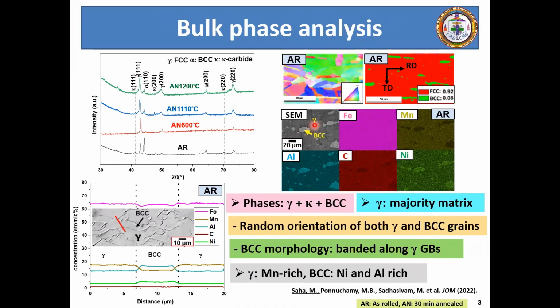and we can clearly observe that the gamma phase, the majority matrix, is enriched in manganese, whereas the BCC phase is enriched in aluminum and nickel. Now the same information can also be inferred from the EDS line scan, which is performed across the gamma BCC region, where we can clearly see the trend that manganese is relatively enriched in the gamma phase, whereas aluminum and nickel are relatively enriched in the BCC phase.